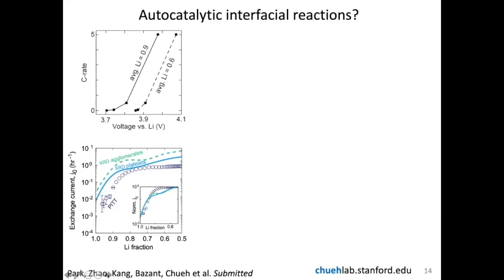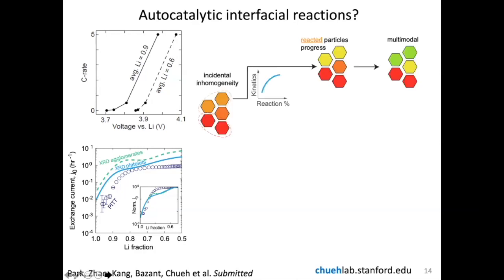To further support that, if you perform your standard relaxation experiment, whether it's impedance or transient measurement, you can also measure the exchange current density. And there you also see the same behavior, that you have a very strongly varying exchange current density. And if you compare this to the diffusion coefficient, you find that indeed the exchange current can become limiting under extreme conditions throughout battery charging and discharging. So if the reaction is limiting rather than diffusion in NMC cathodes, how can this explain the heterogeneity that increases with the rate of delithiation, and the heterogeneity only existing on delithiation, but not on lithiation? And for that, I would like to introduce you to the autocatalytic behavior of the interfacial reaction.